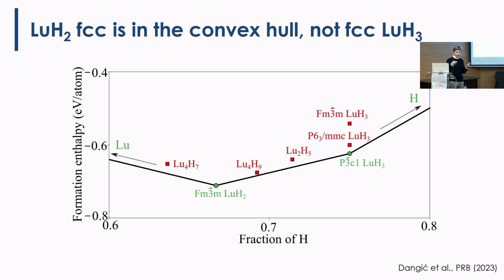So this is what I told you before, we calculated the enthalpies of these structures, and we saw what we expected. So basically, because we know from the X-ray that lutetium is in an FCC arrangement, we have basically two candidates with FCC. Okay, basically the LuH2, Fm-3m, this is FCC, and this is in the convex hull. So basically, if you mix lutetium and hydrogen, it's energetically favored to form this compound in an FCC. And then you have Fm-3m LuH3 up there.